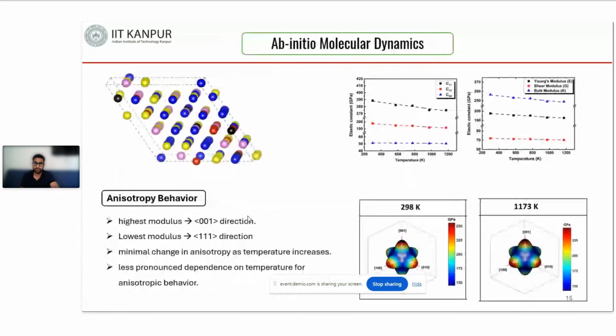We use this ab initio molecular dynamics approach, and first we develop a random structure of the high entropy alloy with the SQS method, special quasirandom structure method, using a tool. We developed this random supercell with 100 atoms. Once we successfully developed this random structure of a 100 atom supercell, we did the ab initio molecular dynamics simulation in VASP and tried to relax the structure at different temperatures. We tested up to 5 temperatures, like 298 Kelvin, 573, 773, 973, and 1173. We did the ab initio molecular dynamics simulation at these temperatures and tried to relax the structure.